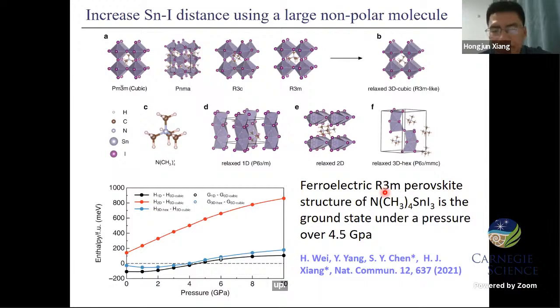So it has this kind of polarization. However, at zero pressure, this structure is not the lowest energy structure. But we found that at a small pressure, for example, 4.5 gigapascal, this kind of three-dimensional structure becomes the lowest enthalpy structure.